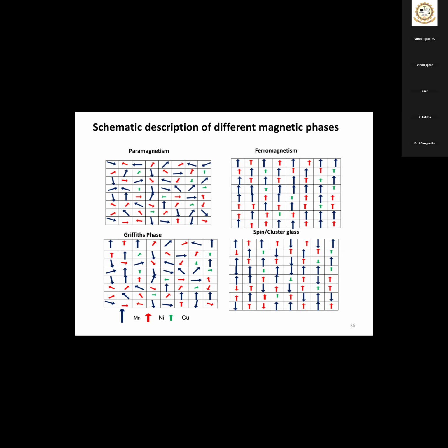Spin or cluster glass means there will be local ferromagnetic ordering, but not entirely along the same direction across all the clusters. Some clusters will be ordered in some direction. The other cluster will be ferromagnetically ordered inside that cluster, but over a large area it will again be ordered in some other way. So your total moment will again be very low. That means you can say it is a random ordering of small ferromagnetic clusters.